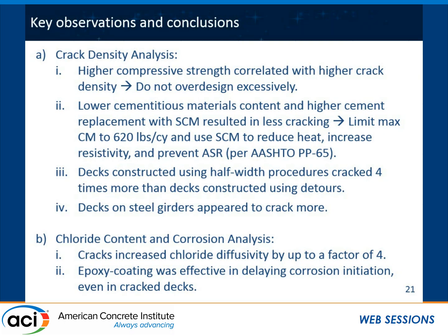On water permeability, it's the opposite, in that crack width makes a tremendous impact. There is a well-known relationship, they call it either a square or cubic relationship, depending on how you define permeability. Your permeability is related to, let's say, a cube of crack width. So if you have a lot of fine cracks, for example in fiber reinforced concrete, at the same density you would get a lot less permeability than if you have one or two big cracks. There is other good work looking at crack width versus transport that I'll be happy to chat about. Thanks.